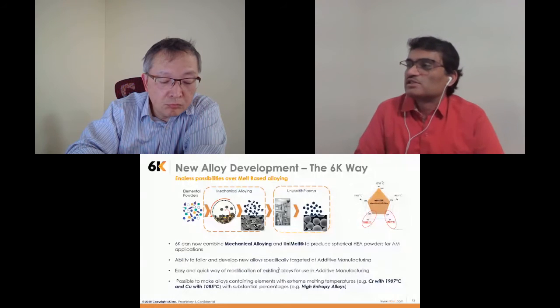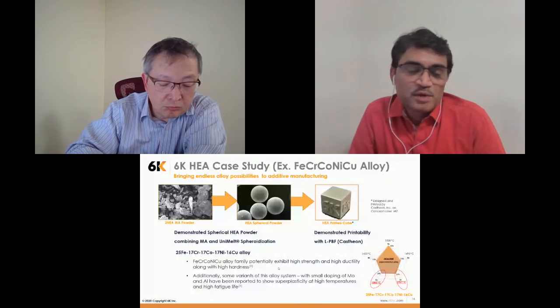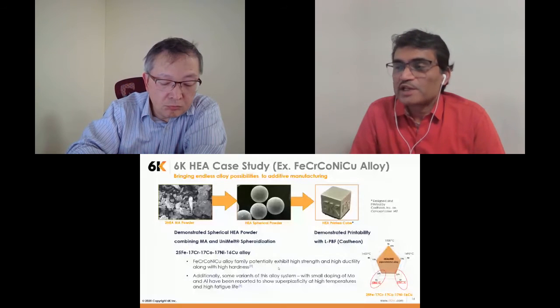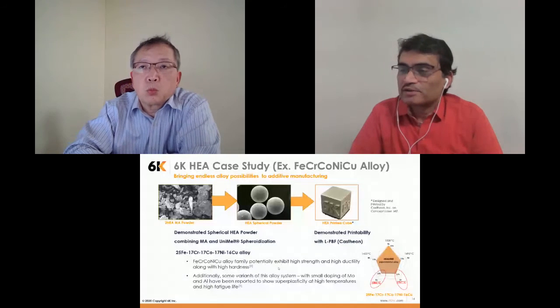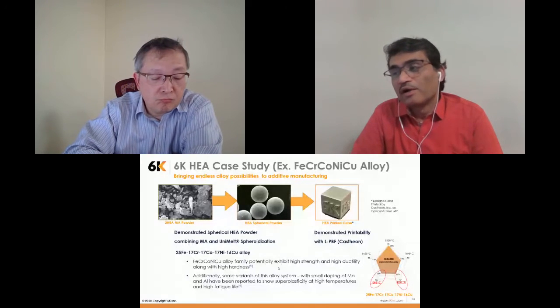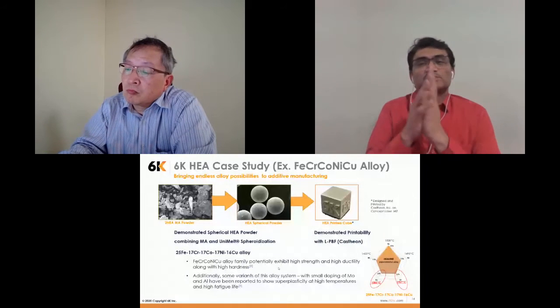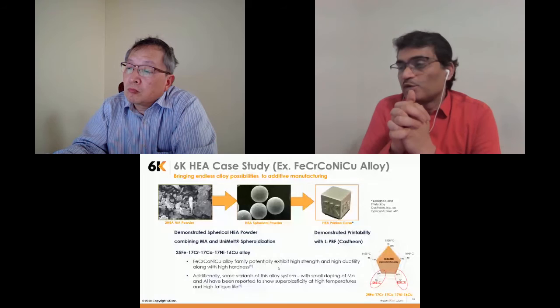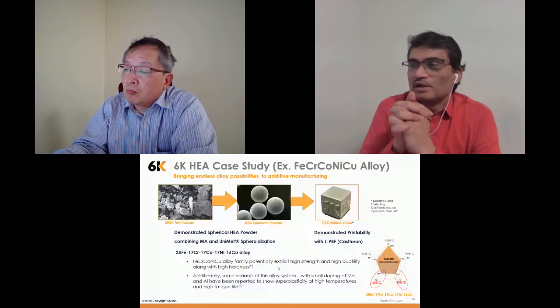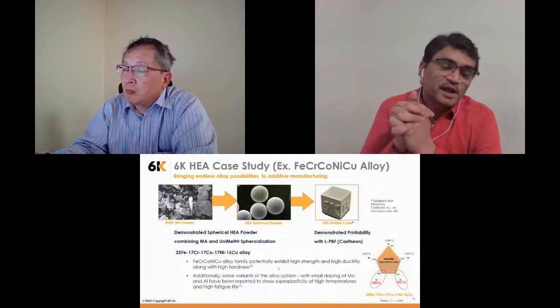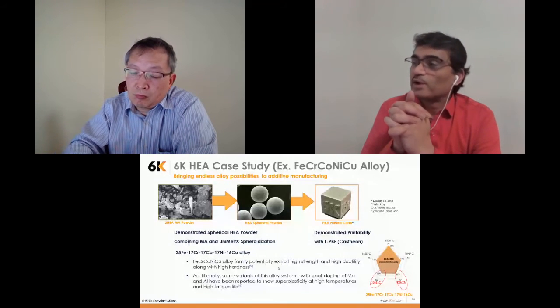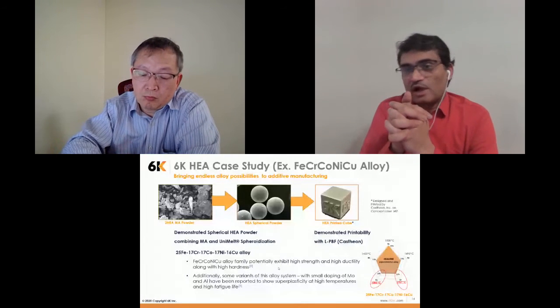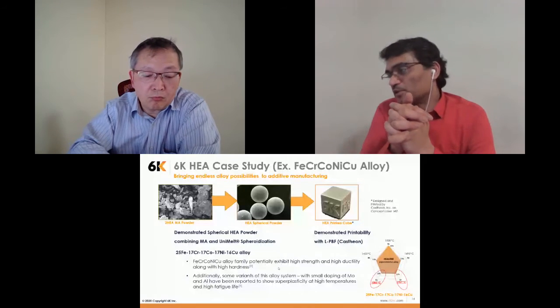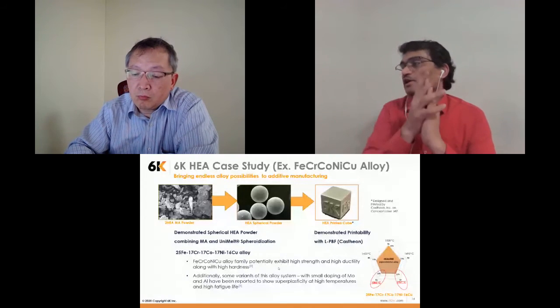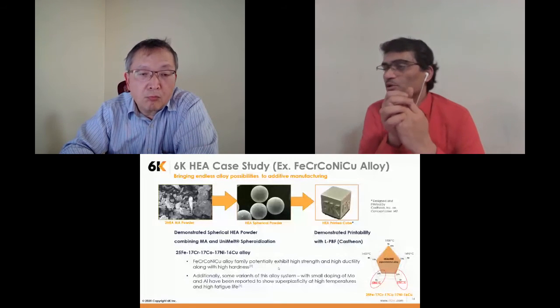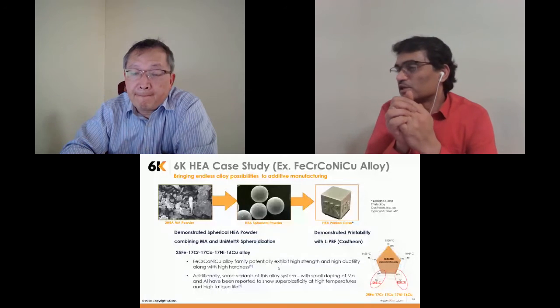In this case study, we demonstrated that we can manufacture this targeted alloy that's 25% iron, 17% chromium, 17% cobalt, 17% nickel, and 16% copper. So this is a near equiatomic composition. We have successfully manufactured it by mechanical alloying, and then we have successfully spheroidized it. And after spheroidizing, we have also printed it with the help of Castheon. Castheon actually designed and printed this cube that shows 6K and 5 elements on the other 5 sides.